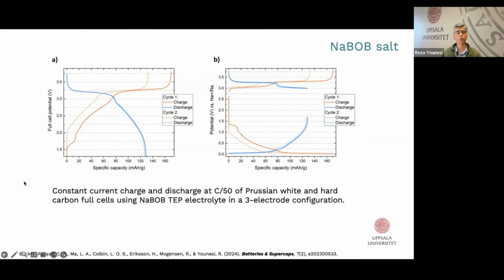From these results, we can learn that NaBOB is decomposed very early in this electrolyte solution, perhaps way before TEP. But we found that this electrolyte itself, with no additive, is not really stable for long-term cycling, and the first cycle Coulombic efficiency is not really high. So the electrolyte needs to be optimized to be practical for any commercial sodium-ion batteries.